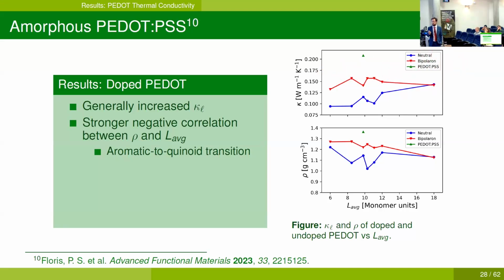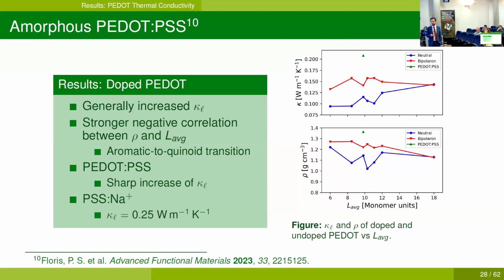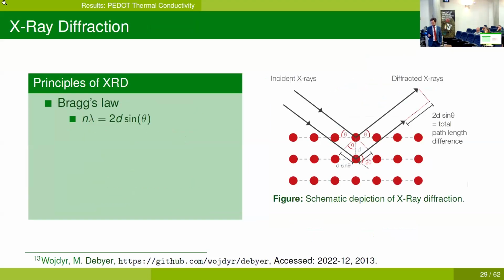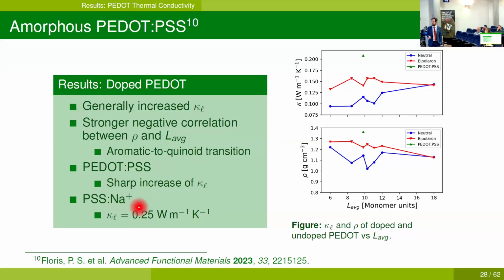On the other hand, when we add PSS to the sample, we see a sharp increase in kappa L. So the sample with PSS is this green triangle here, which has a much higher kappa L, and this is only due to PSS itself, since it has a higher thermal conductivity and it increases the overall thermal conductivity. You could say that maybe PSS is just changing the morphology of PEDOT, and you would have a point. But we also calculated the thermal conductivity of PSS alone, and this is much higher than all of these values. This is 0.25, and this is right above here, which we cannot see.